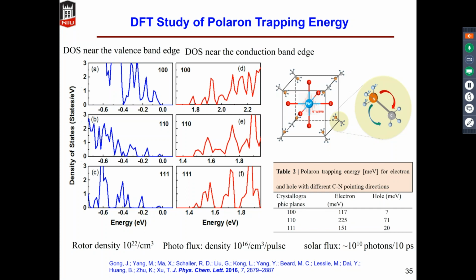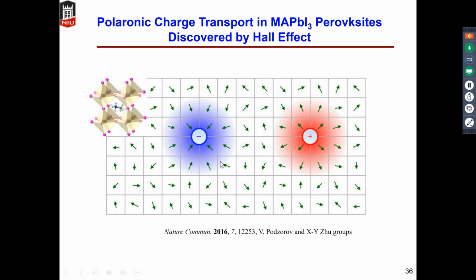But this is not a single rotor and a single charge interaction. It involves all the rotors nearby the photo-induced charge. So it forms this so-called polaron interaction. And we also noticed another paper published by Podzorov and Xiaoyang Zhu's group, and they also discovered this polaron interaction from the nearby charges with the photo-induced charges, and this is also a polaron interaction.